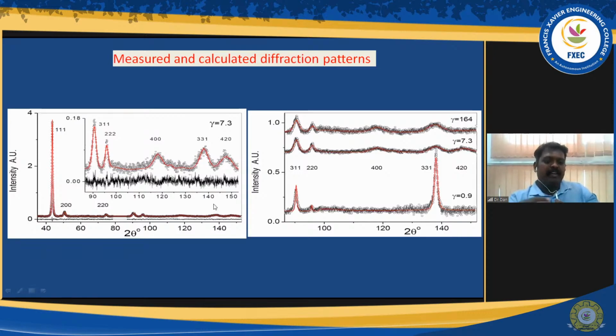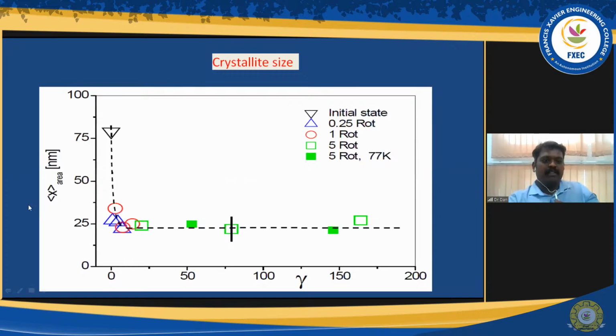Then they studied by the line profile method. They measured the dislocation density of the material after the HPT process. They also calculated the grain size from this calculation, and they got about 25 nanometers after 5 rotations. You can see how much they refined the material. In my case, I was only able to do normal conventional rolling and reached 200 nanometers, but in this case they were able to go down to 25 nanometers.